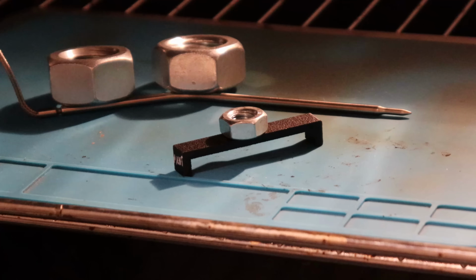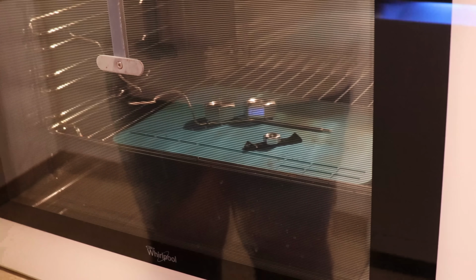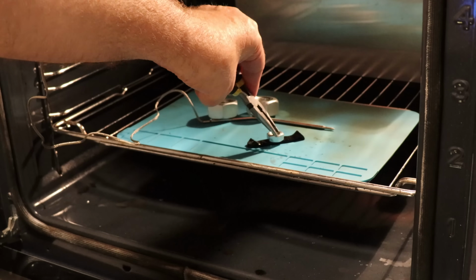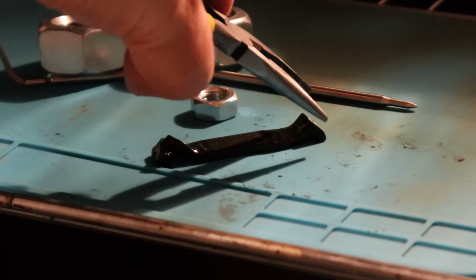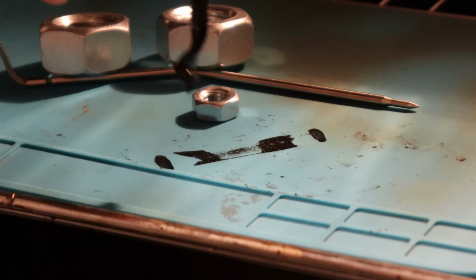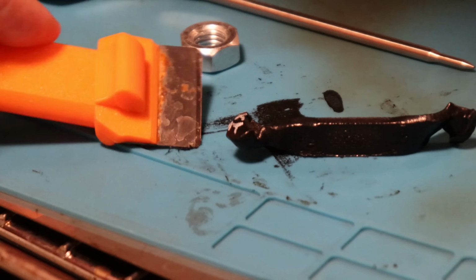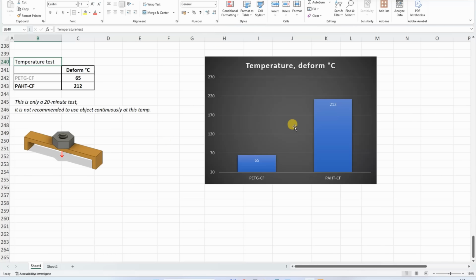Temperature test in the oven. Even the recorded time-lapse is sped up here. The first deformation I noticed at 212 degrees Celsius, but then it deforms very suddenly, so be careful, don't go closer to this temperature. Soon I stopped the experiment, but it was really melted and stuck to this silicone mat. I could easily scrape it off, and don't worry, I finished this outside. Another very important property of this material, it is very temperature resistant, even if I didn't anneal it. Now be careful, don't go closer to these temperatures, because it deforms very suddenly.